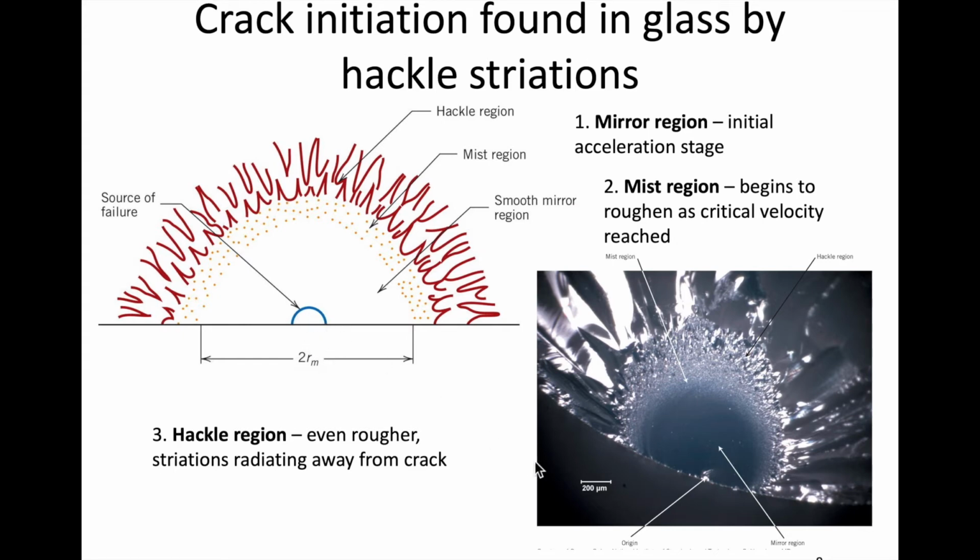You can identify that because, again, these markings, like those chevron marks, tie back and radiate out from the central point of failure. Oftentimes they're small, but we can see them. We'll use the microscope in the lab to identify the failure, or to look at some of the fracture surfaces for your glass, and you'll hopefully be able to see similar aspects to this.